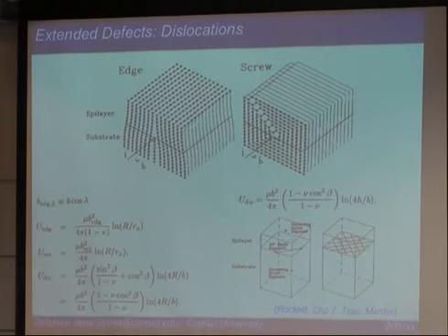So that's the length of the dislocation, and there's a vector you can write along the length, right? And remember, when we walk around here, we are going to miss a step in the end. When we come back, we won't be back to the same position, and that missing length is called the Burgers vector, right? And it's typically of the order of a lattice constant, as you can see. Now, which lattice constant, this or that, we can figure out, but essentially most lattice constants are very similar.